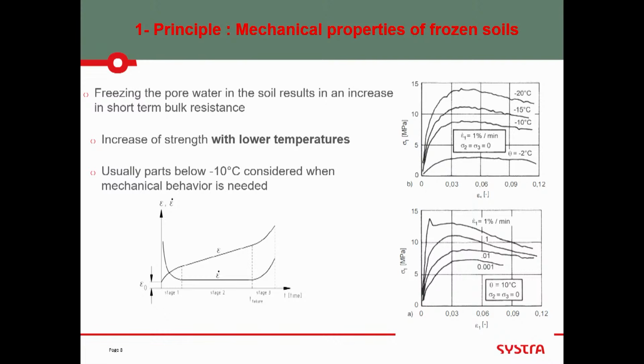So what happens is the strain velocity is quite high. We are crushing the sample at a rate of 1% per minute. There is a peak, and UCS is about 13 MPa. If you are crushing slowly at 0.01% per minute, it's 8. And if you are crushing at 10 to the minus 3 per minute, it's 6. So you see that between this 1% at 13 and this 10 to the minus 3, you get a ratio of 2. So we know that loading is important. And when we crush a sample, we crush it with a given speed.